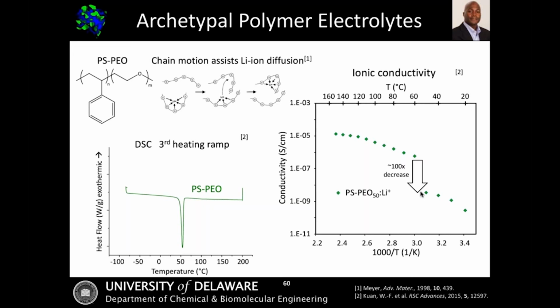So what's happening there? We can go look at DSC data, and we see that we get melting and crystallization of that polyethylene oxide domain in those PSPEOs. Upon crystallization, I essentially arrest or significantly retard chain motion, which means that I get no lithium ion conductivity. And you might say, well, why is that important? If I'm operating a material that I want to use in, say, a car, operating in this range is reasonable and I can deal with this particular polymer system. However, if I want to use my laptop or cell phone, many times I want to be at temperatures around 20 to 40 degrees, and so this conductivity down here at 1 × 10⁻⁹ is completely unacceptable.